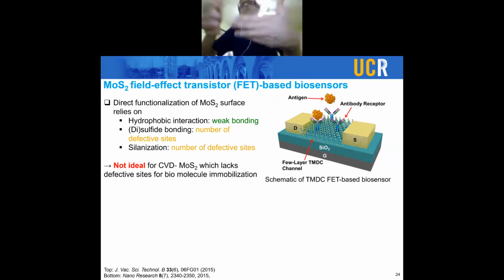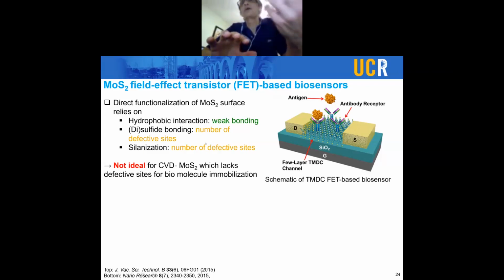Traditionally, people always use exfoliated MoS2, which has several defects in it, and then they attach the antibody using either the sulfide vacancies or sulfide defective sites, or silanize it, because silanization requires some kind of molybdenum oxide or molybdenum hydroxide present there. And then they go ahead and try to use that.